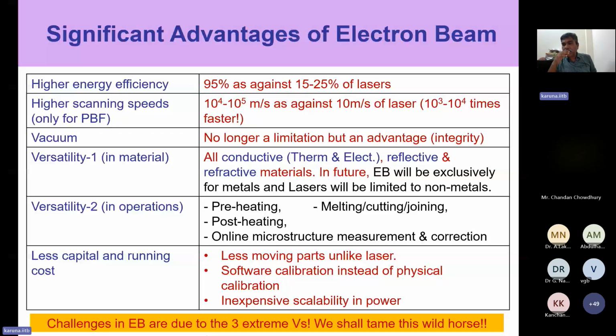We are able to realize the vacuum within about 10 to 15 minutes, the complete chamber of 2.1 meter by 4 meter height. So that is under control. But when you produce the whole thing in vacuum, absolutely no contamination happens, because air molecules are not there. No other molecules are there. Therefore, the part you produce is shiny all the time. That means it is pure.